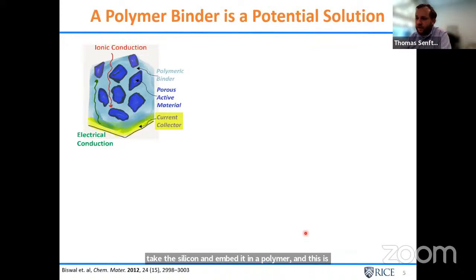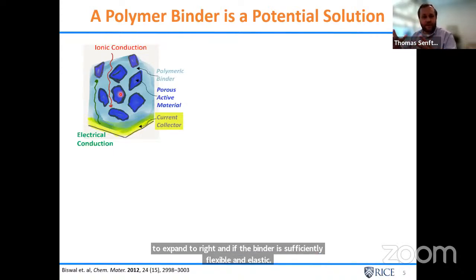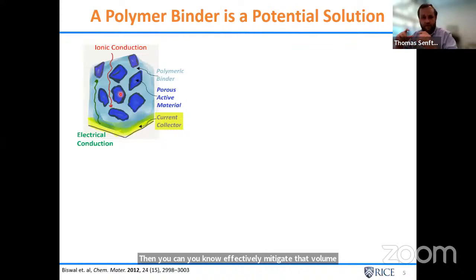In particular, we're going to talk about a system that was discovered or developed by our collaborator, the Biswal group, where the idea is to have mesoporous silicon that's embedded in this polymeric binder. The idea being that when the silicon expands, it has somewhere to expand to, right? And if the binder is sufficiently flexible and elastic, then you can effectively mitigate that volume expansion in the collective electrode, even though the silicon itself is going to expand.